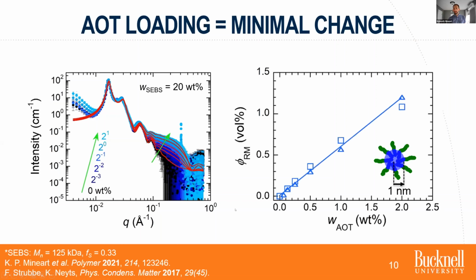And we see, just like I mentioned before, this model captures this plateau lifting with AOT concentration in these gels. And what the model basically tells us is that, first off, the size of the reverse micelles remains constant across changes in AOT concentration, and the core specifically is about 1 nanometer in radius. And also that the volume fraction of reverse micelles in these systems is linear with the weight percent loading of AOT. And this tells us basically that the AOT that's added continually forms more reverse micelles. And we have separate experiments, which I'm not going to show data for here, that confirm that we're above CMC at basically all of these concentrations and over all of the diffusion experiments that I'll show you data for later. And so we've got a lot of AOT reverse micelles and very few single AOT molecules in these systems.